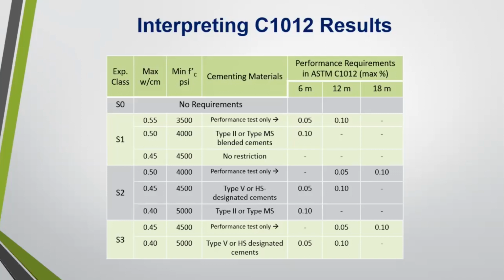If you want to drop that down to a 0.40 water cement ratio and a 5,000 PSI 28-day strength, it's recommending a type 5 or a C595 cement with an HS designation. And you still have to meet performance requirements of 0.05% at 6 months and then 0.1% at 12 months. So this is where we're kind of getting our guidelines and protection in terms of addressing the sulfate mitigation, sulfate attack mitigation.